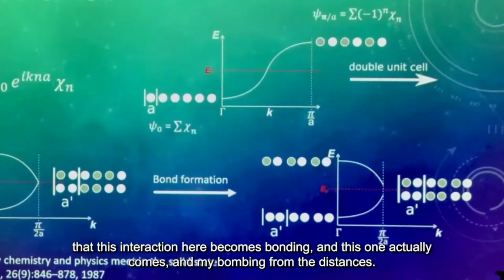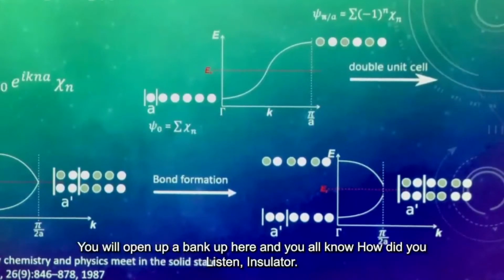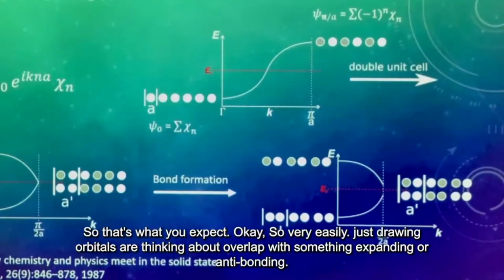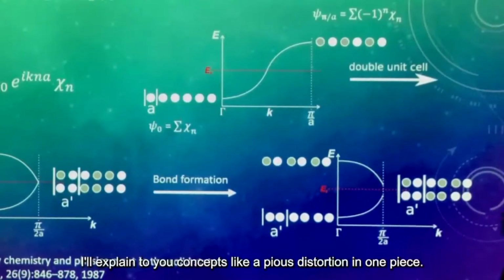And if you do that, this interaction here becomes bonding, and this one actually becomes anti-bonding. From the distances, you will open up a band gap here. And you all know hydrogen is an insulator, so that's what you expect. Okay, so very easily, just drawing orbitals and thinking about overlap, whether something is bonding or anti-bonding, can explain concepts like a Peierls distortion in 1D.